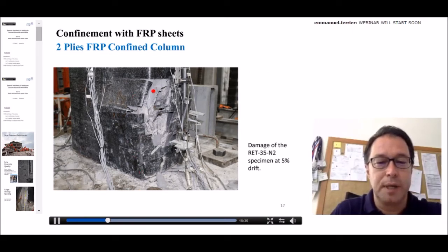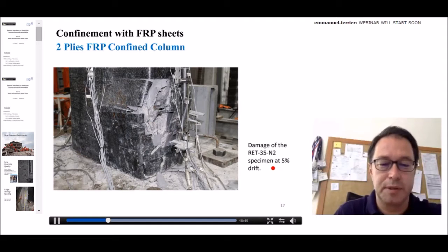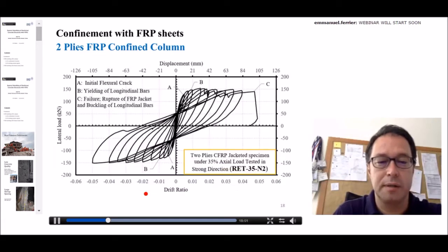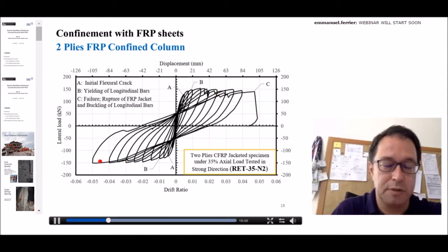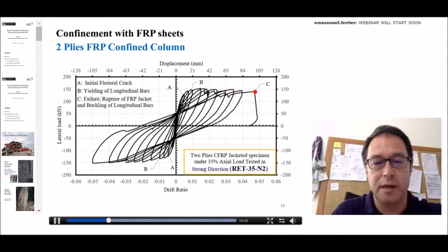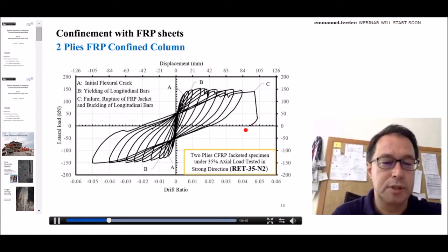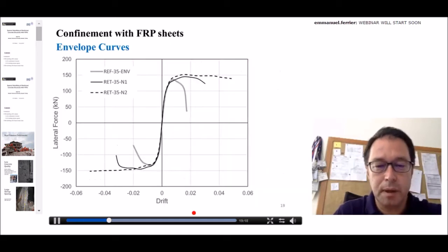If you look at the column with two plies of FRP sheets wrapped around the column confinement zone, this photograph shows us the appearance at 5% lateral drift, almost more than double of the reference specimen. Look at the load displacement diagram. As you see, we could go up to 5% drifts without a significant loss in strength. But stable hysteresis loops around 5% drift, upon rupture of FRP sheets, as expected, the strength is lost suddenly. But you can see the obvious improvement in the behavior.